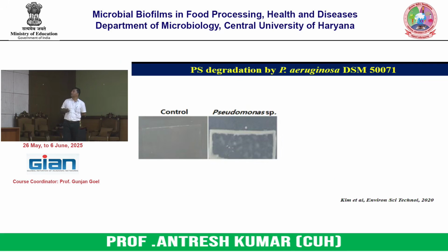And this is one of the research studies on Pseudomonas aeruginosa DSM 50071. This particular strain they have isolated from insect larva, and they grew this strain on a film of polystyrene. This is the control film. This is the microorganism grown on the polystyrene film, and this white is the growth of the Pseudomonas species. It means this Pseudomonas is happily growing in the presence of polystyrene in the minimal media.